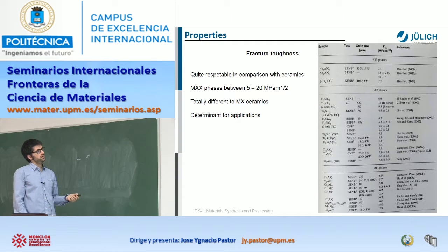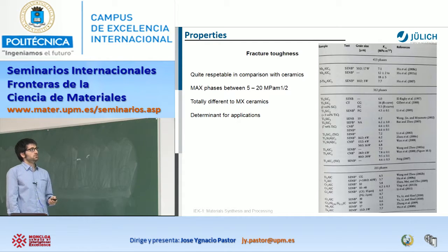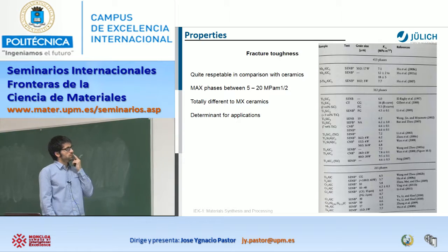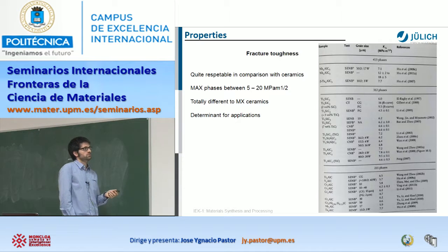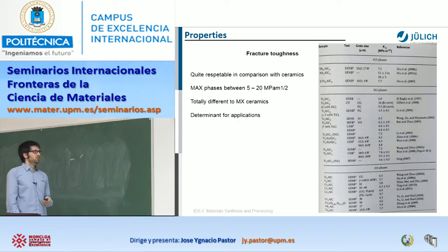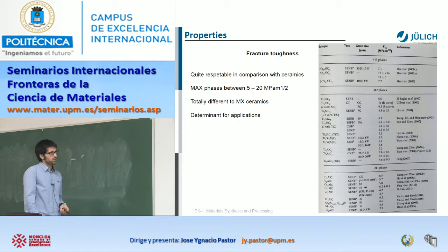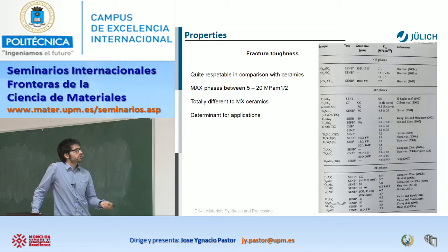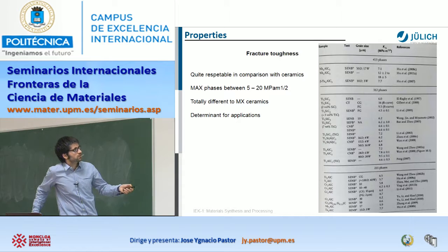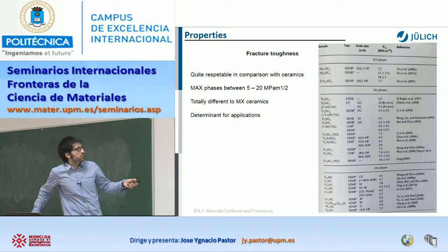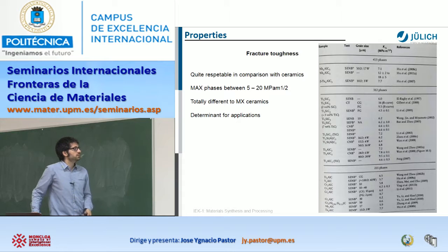Well, the values in MAX phases can normally be tailored between 5 and 20. That, to be honest, is a quite respectable value in comparison with other ceramics. Of course, it's impossible to achieve these values even in maybe silicon nitride or other materials that have a really good response, but not like that. If you want to go to these values, obviously you should go for the CMCs. Yeah? These are just values from the literature, but you see 18 even in other phases, or 16s, depending on the grain size obviously, but different values.